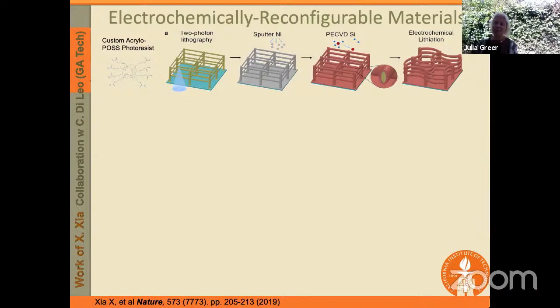Since we're on the topic of electrochemistry, we have explored this concept of electrochemically reconfigurable materials. So if you look at a tetragonal architecture, much like the architectures I've been showing up to this point, and now as the active anode material, you effectively would deposit a very thin layer of silicon. So it'd be about 100 nanometers of silicon.